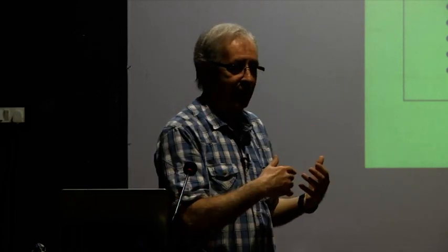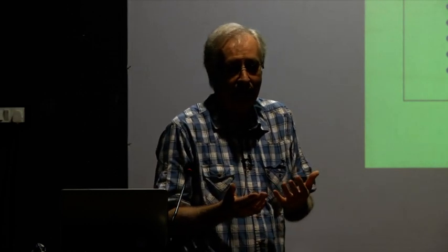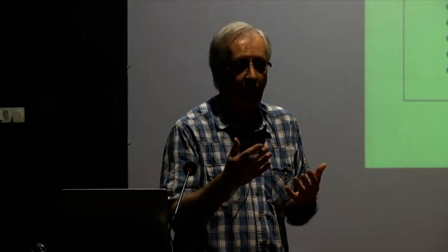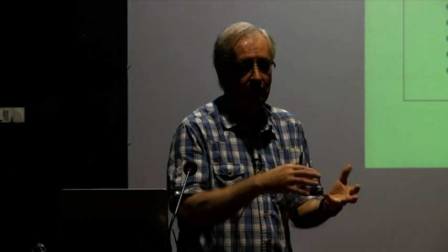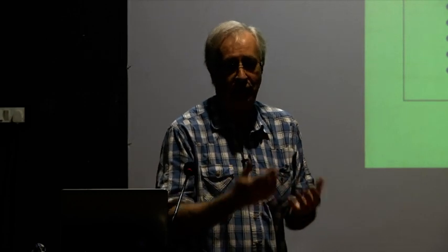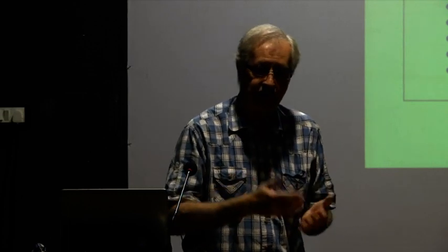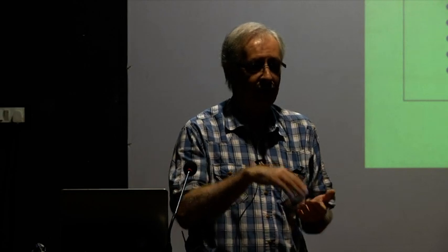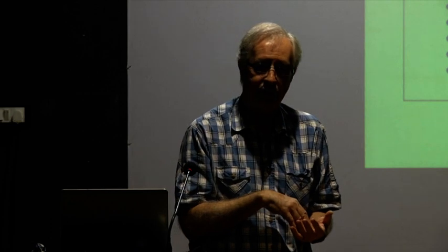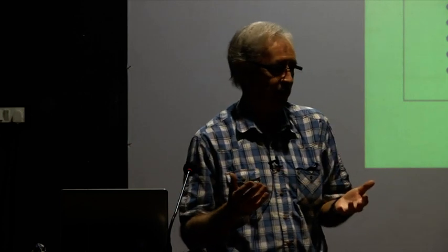So now we have the magnetic version of this thing. It's the same thing. It's a martensitic transition. You don't have to give it a new name. And you can cool it, change the shape, detwin it, and warm it. You'll get back to the same shape. But additionally, what we have about nickel manganese gallium is that it is ferromagnetic in the austenite phase, and it is ferromagnetic in the martensite phase. So you have a chance of doing something with a magnetic field. You don't have that in nickel titanium. It's non-magnetic.